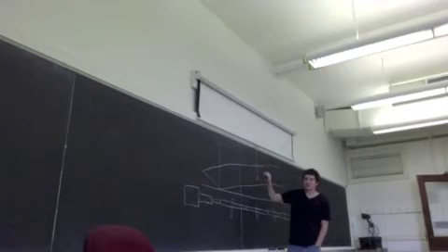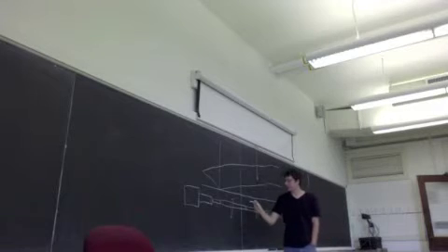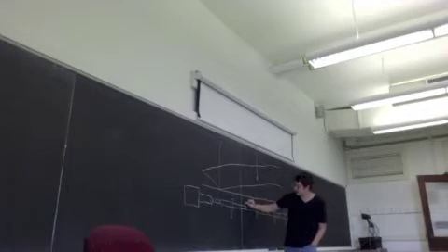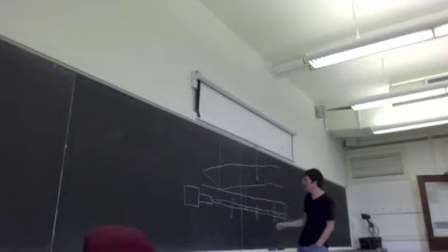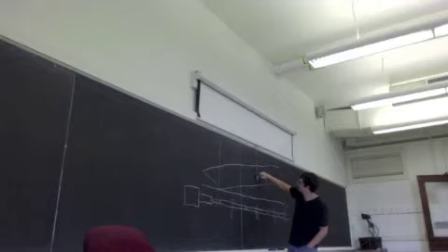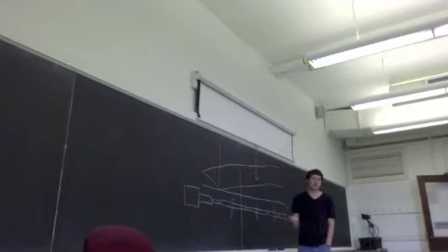Now, how we turn this information into stress and strain in the sample is to simply record the strain at this strain gauge and the strain at this strain gauge. This is known as the incident pulse, this is known as the transmitted pulse, and there will also be a pulse reflected from the sample because of differences in impedance, wave propagation impedance, between the materials.